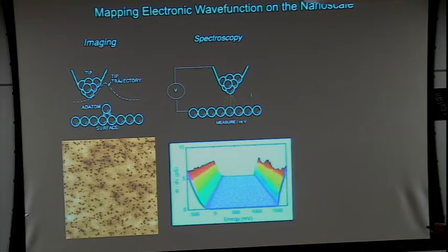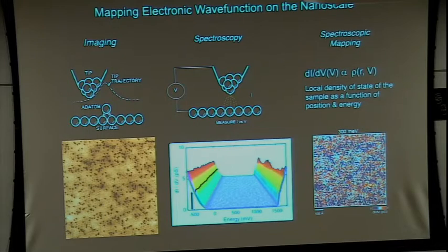And of course, the power of the STM is you can do this experiment at every pixel of your surface, and with that you can build a local map of the density of states. The tunneling current between the tip and the sample is related to the integral of the density of states between, say, the Fermi energy and whatever voltage you apply between the tip and the sample, but it convolves the density of states of your tip and your sample together, okay?